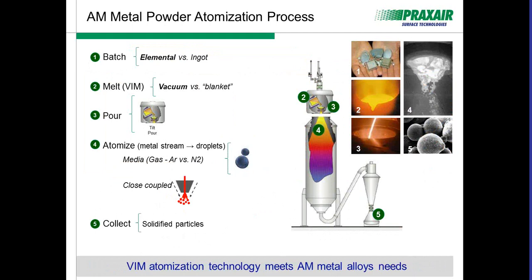When we talk about melting, we want to be able to melt this powder in vacuum. So that drives out, as I said, all the air, and instead of using a blanket material, which simply means you're melting in air, but you're basically using a cover gas like argon to prevent the metal within the pot from oxidizing during the process. Pouring, we take advantage of tilt pouring, because really you can control the flowability of the liquid metal during the process in a much more controlled manner. And in controlling your metal flow rate really leads you to controlling your gas to metal ratio, which will yield the highest quality powder as you move forward.